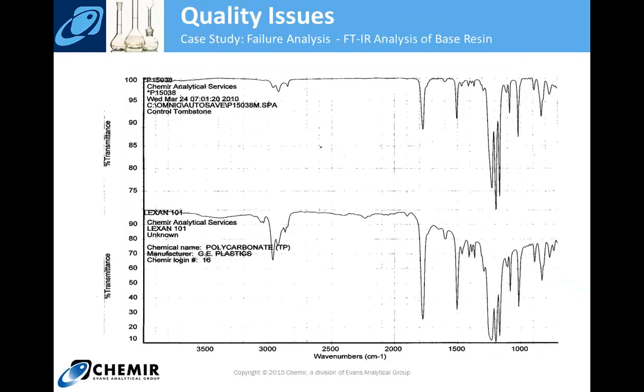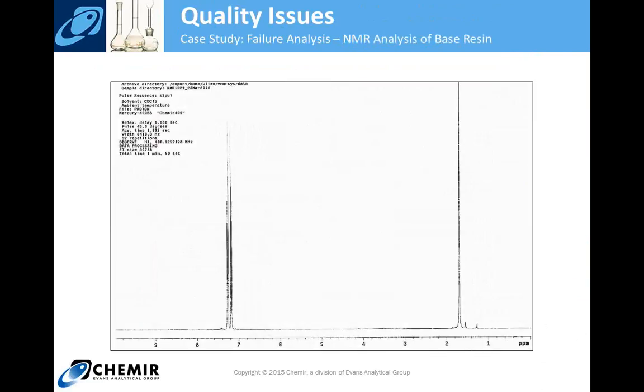Some analytical tools that were used: for those out there who know analytical chemistry, this is infrared spectroscopy, providing a chemical fingerprint of just the base resin, looking at a good material now. Getting a chemical fingerprint of what the polymer should be, and the fingerprint for the control samples we analyzed, shows that it's a type of polycarbonate, as it should be. A different analytical tool, just to confirm the polymer and some of the polymer structure, is NMR, nuclear magnetic resonance spectroscopy, which provides more structure of organic molecules. The NMR analysis confirmed that we have a basic type of polycarbonate resin, as it should be. So two different analytical tools show that the resin is made of what it should be. Someone wasn't substituting a polyethylene or a PVC when it should have been a polycarbonate.